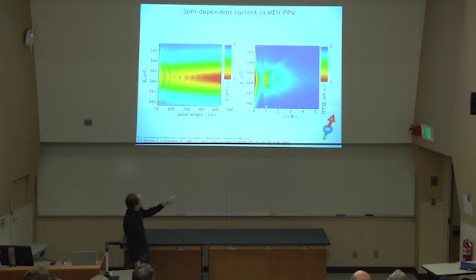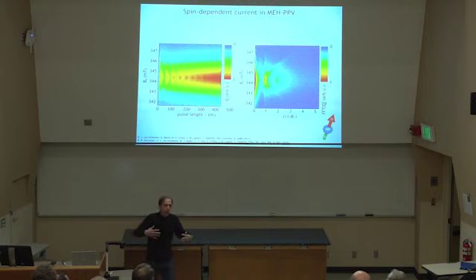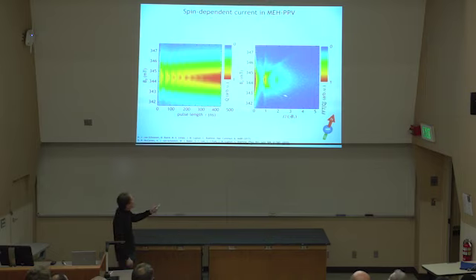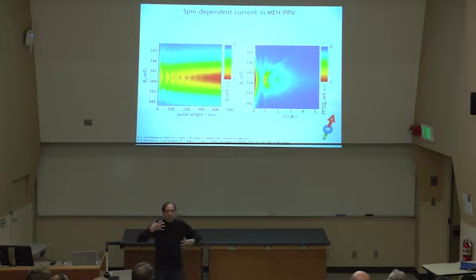And you may say now, well, if gamma times B1 corresponds to 1, and that corresponds to a spin 1/2, then is that at 2 maybe a spin 1? It's not the case. The Rabi frequency of a spin 1 is gamma times B1 times square root of 2, which we don't see here. So this is essentially a spin beat oscillation. So it's a beat oscillation between 2 spin 1/2 systems.